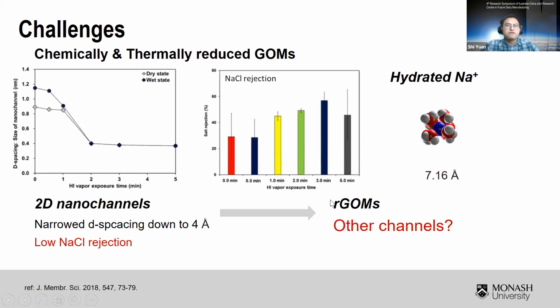However, we are also facing some challenges. Like in this one, researchers prepared RGO membranes with chemical and thermal reduction methods. Even though the channel size decreased to 4 angstrom, which is quite small, way smaller than the hydrated sodium cation, the rejection of this cation is quite low. It is way lower than the theoretical value, with only about 40% rejection of sodium chloride. So this phenomenon makes me think there might be some other channels for water and salt transport other than the well understood 2D nanochannel. So the understanding of other channels is the objective of this work.